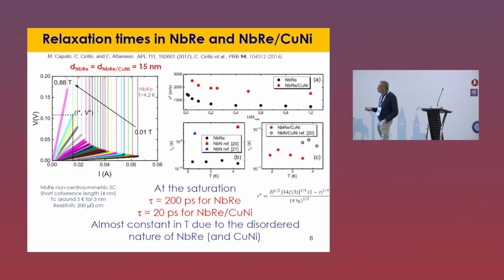I want to start from the end. These are some final results that we obtained some years ago on a new material, which is niobium rhenium, a non-centrosymmetric superconductor, which we started to use for different purposes. The most important feature of this superconductor is that it has a very short coherence length, of the order of 4 nanometers, which means you can have quite high TC also for very thin niobium rhenium films. In our case, we get something a bit higher than 5 K for 3 nanometer thick films. Also, the resistivity is quite high. So already these two characteristics make this material appealing for superconducting single photon detectors.